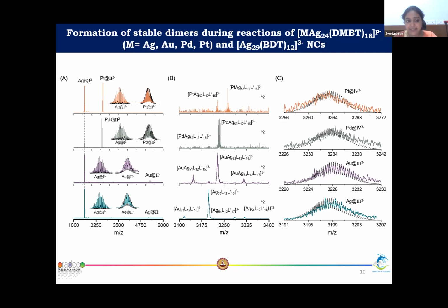People have already seen that when the probe distance is more, the smaller droplets will be abundant there, and the intensity of the gaseous species increases. When the probe distance is less, whichever species is more abundant in the solution, that intensity is more. So we have also checked our dimer species by varying this probe distance, and the dimer species is found for all the varied probe distances.